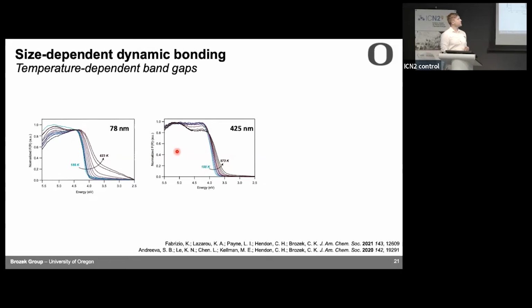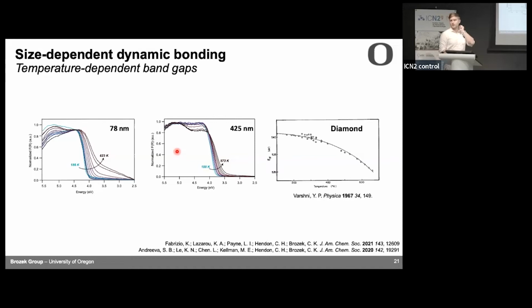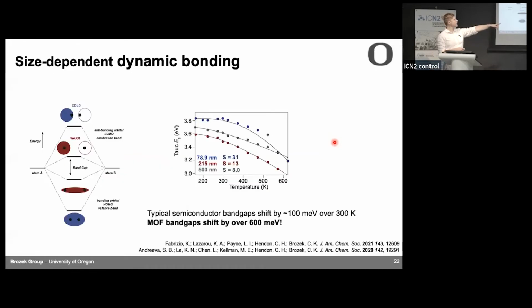What this reminded me of was how semiconductors in general, so diamond, silicon, germanium, when you heat them, their optical gap gets smaller. But it typically only gets smaller by, I don't know, 100 milli-eV or so, not as severe as this. So this was unexpected. But how do we think about this? Why does this happen in a normal semiconductor? Well, you can think about it in terms of typical molecular orbital theory. At low temperatures, your atoms are close together, and so the bonding orbitals are really low in energy. They're really stabilized. And it means that your anti-bonding orbitals are really high in energy. So that means it's a big gap.